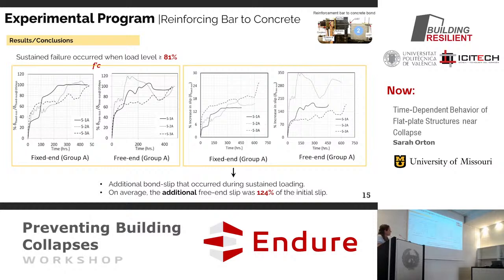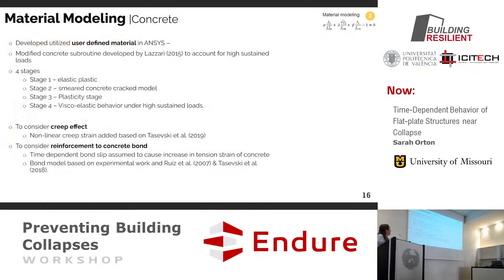Another thing that's interesting in this is the additional free end slip was about 124% of the initial slip. So you load it and move some, and then over time it moves that much again and a little bit more. And so you're talking about a whole lot of slip in the connection even before failure. And so that is part of what causes increasing deflection in our reinforced concrete structures, a slip between the reinforcement and the bond. And the concrete.